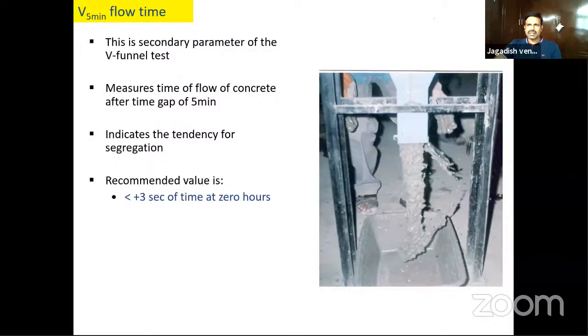So when you open the gate, it will pass slowly through the narrow end, because the concrete is not good. The recommended value says the maximum should be less than plus 3 seconds. That means if the V-funnel time is 8 seconds, the V5 minutes flow time should be 8 plus 3, that is less than 11 seconds. You should get that V5 minutes flow time. This is how you can see the video.